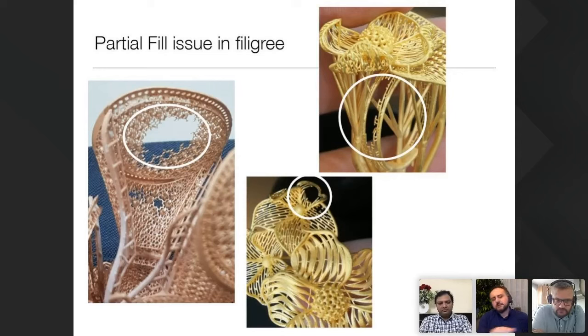I agree. Let's say on the left-hand side, this bangle or the part with the big hole, if you put a feed in the middle of that filigree, obviously the metal will also be entering from that area and will fill it. So if you don't have big pressure, or if you have issues with your casting machines and other things, in general you need to always check your feeding. I mean, your cast.